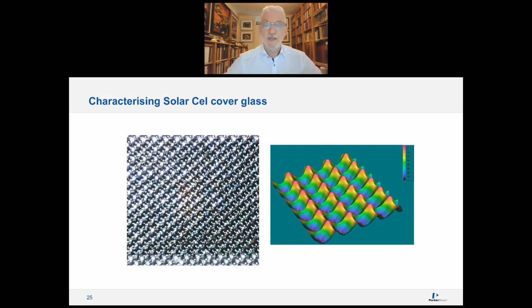For cover glass, you can have something similar. There have been several attempts to get more light into the solar cell, not just by the TCOs, but also by changing the structuring or making a pattern on the solar cell cover glass. One of the popular patterns was the so-called indented pyramid structure, like you see here. It's rolled into the glass during manufacturing when the glass is still soft. The right picture shows a scan with a profilometer to get some idea of how a surface like that looks. The problem was for the glass industry making accurate measurements for that.